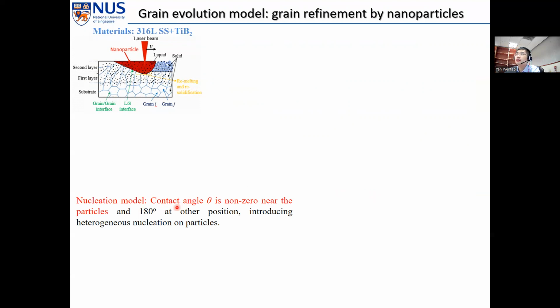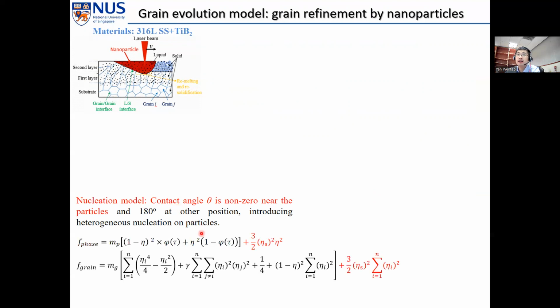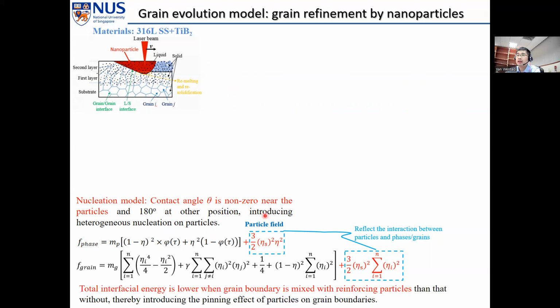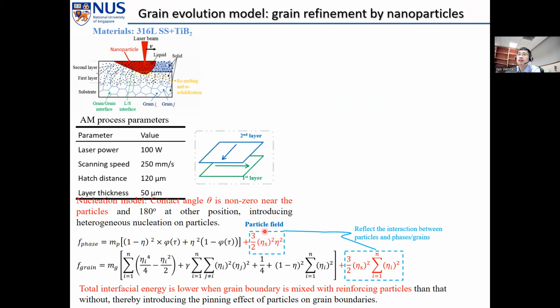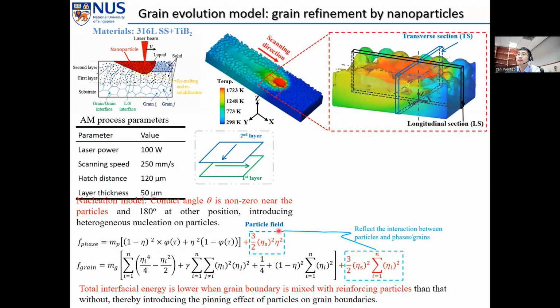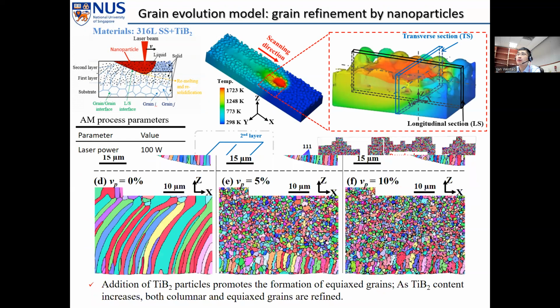So there are actually two effects. One is in the nucleation, they can introduce more nucleation sites. And second is during the grain growth, they can slow down the grain boundary movement so that they can slow down the grain growth, which is called the Zener-Pinning effect. So we incorporate both effects in our simulation, and then we compare the simulation with experiments.